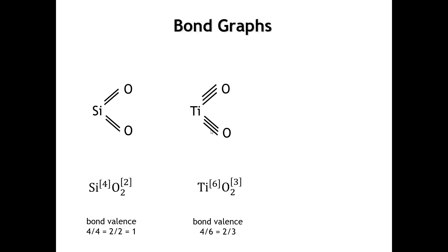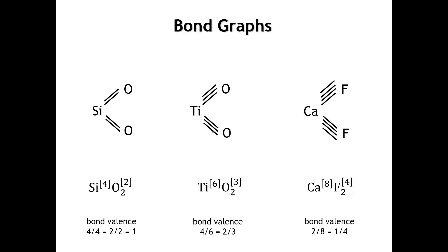Drawing two lines does not mean a double bond — that's just symbolism to determine coordination number. An important point is that bond valences in inorganic compounds don't need to be integers, unlike in organic chemistry where carbon must make four bonds with a valence of four; here the valence can be a fraction. For calcium fluoride CaF₂, calcium is bigger still with a common coordination number of 8, which means fluorine must be 4-coordinate — tetrahedral fluoride with eight fluorides around each calcium in a cube.